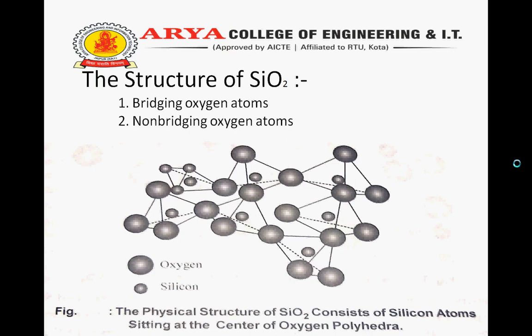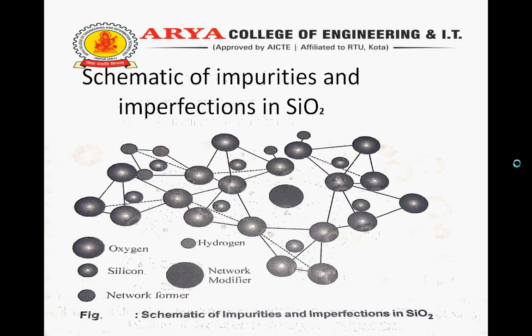A variety of impurities can also exist in thermal oxides. Some of the most common are water-related complexes. If H2O is present during the growth, one reaction that can occur is the reduction of a bridging oxygen site into two hydroxyls: SiOSi equals SiOH plus HOSi. These hydrogen atoms are only weakly bonded and can be removed under electric stress or ionizing radiation, leaving a trap or potential charge state in the oxide. This is shown in the figure.